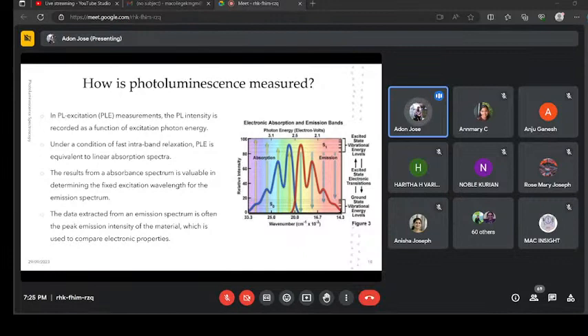Next, we are going to introduce how we actually measure photoluminescence. In photoluminescence excitation measurements, the PL intensity is recorded as a function of excitation photon energy. Under certain conditions, for certain materials, the photoluminescence excitation spectrum is found to be equivalent to the linear absorption spectrum. This result from an absorption spectrum is very crucial in determining the excitation wavelength for the emission spectrum. The data extracted from the emission spectrum is often the peak emission intensity of the material, which is used to compare its electronic properties.